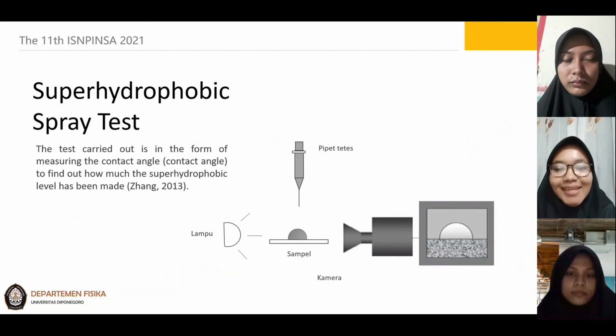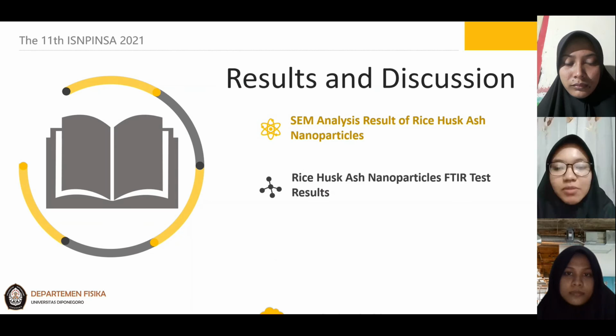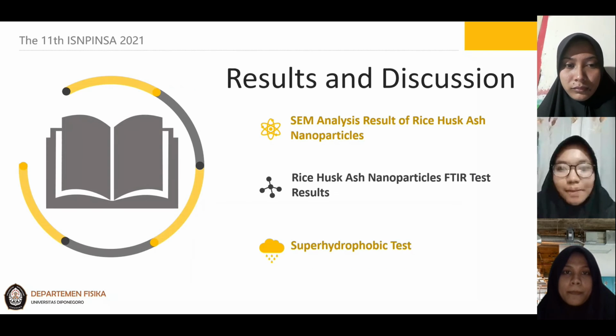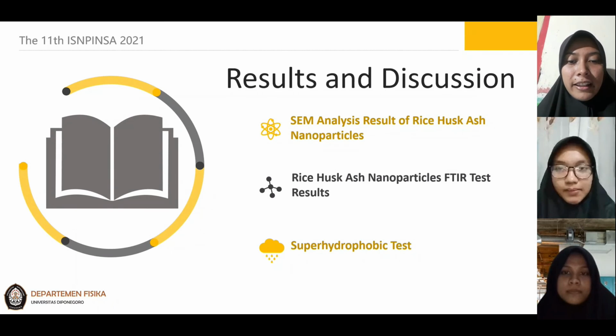Superhydrophobic spray test. The test is for measuring the contact angle to find out how high the superhydrophobic level is. To validate the observation, the test is repeated 3 times. Next slide. Results and discussion. First, SEM analysis results of rice husk nanoparticles. Second, rice husk nanoparticle FTIR test result. And third, superhydrophobic test. Next slide.